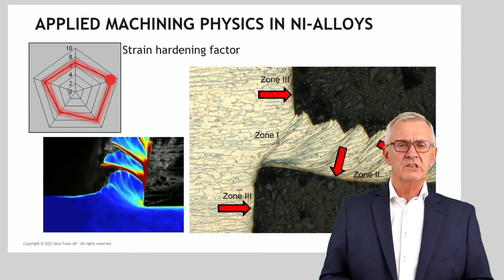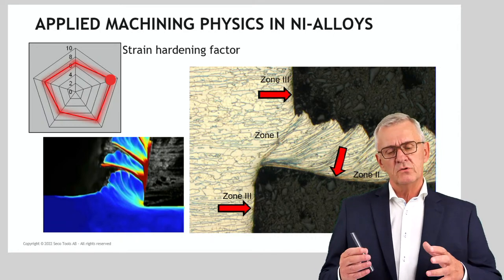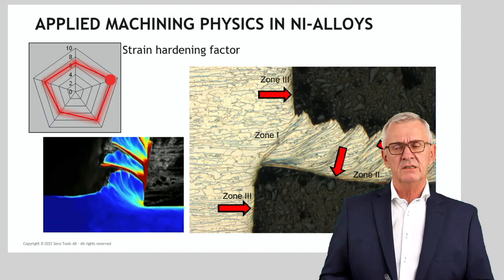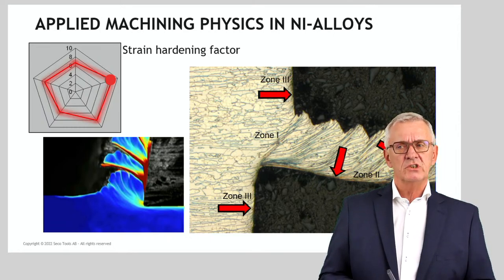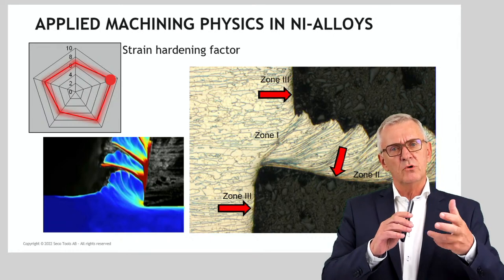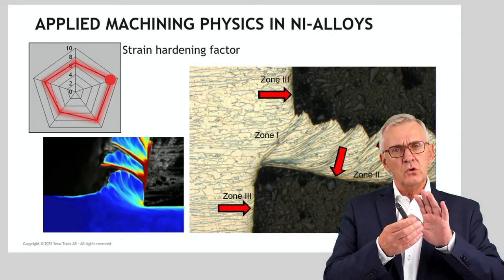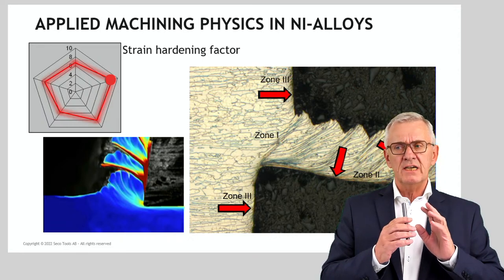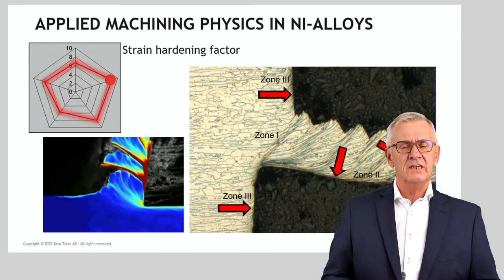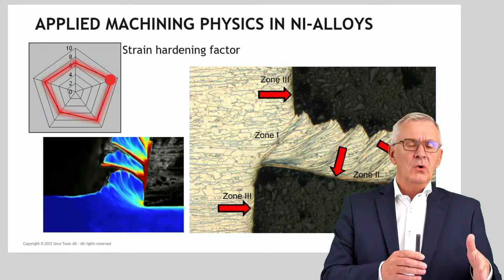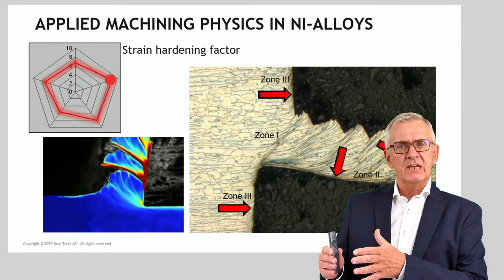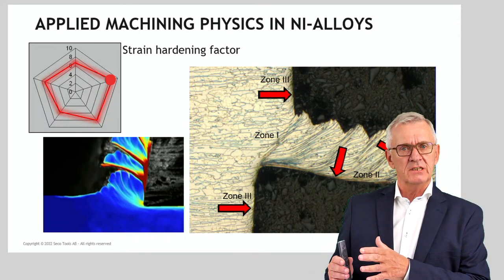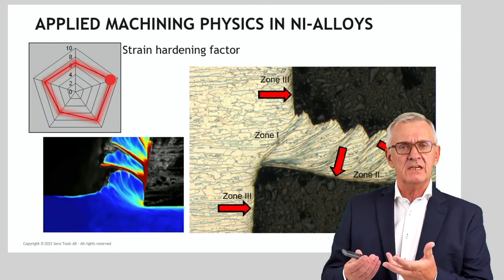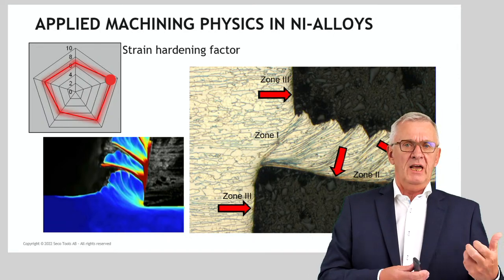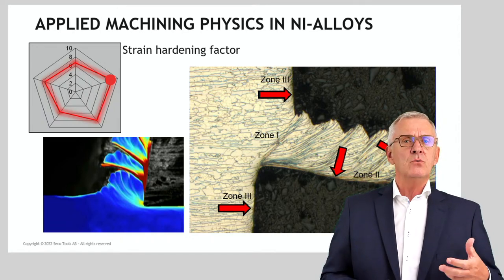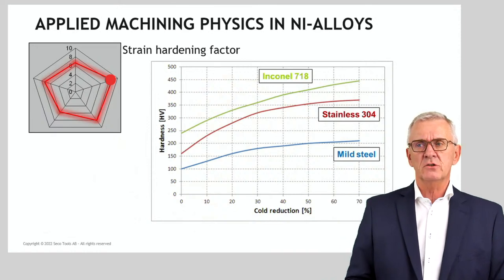And strain hardening goes even further, but I just want to mention it to give you a complete picture, because if you look at chip formation in nickel-based alloys, what you see is that deformation does not only take place in the workpiece material, but the chip which is formed is also being deformed. So potentially you create a chip with a hard layer, and that hard chip will lead to more abrasion. So in the beginning, perhaps you didn't expect abrasion when you machine nickel-based alloys, but during machining, due to strain hardening of a chip, it could be that the chip behaves much more abrasive towards the cutting edge than what you thought from the beginning. It's an aspect not to forget.